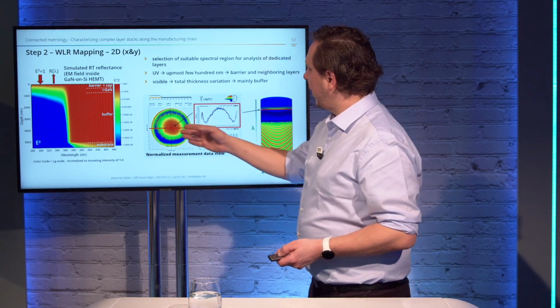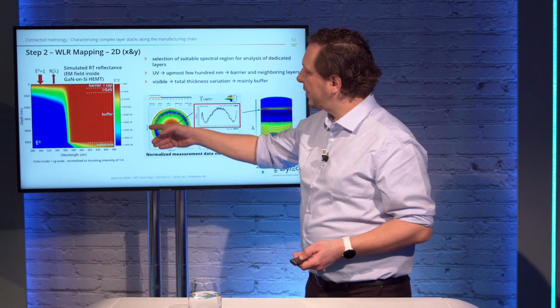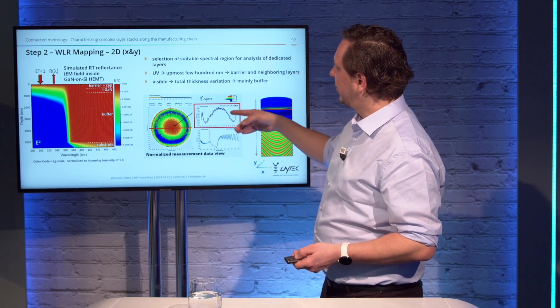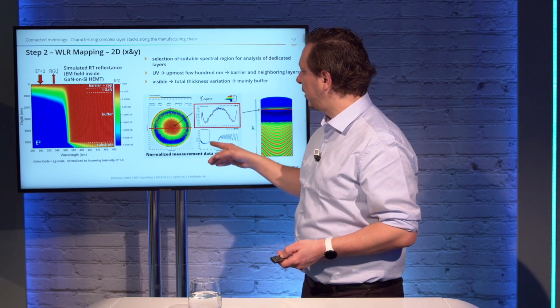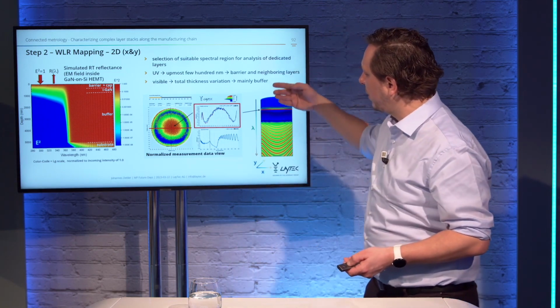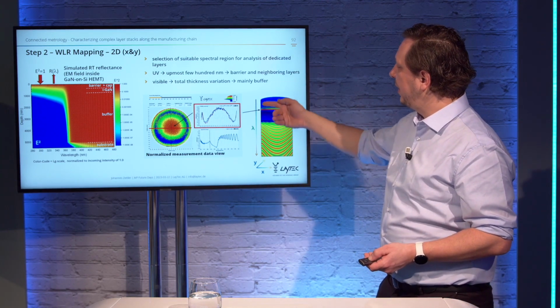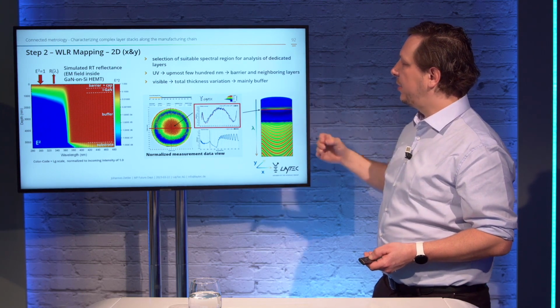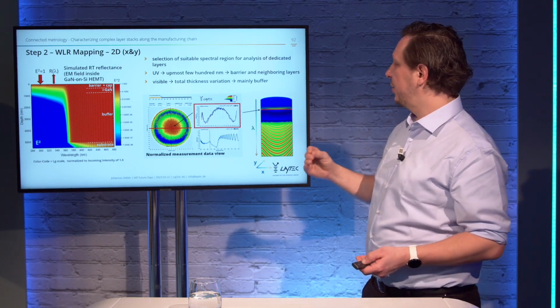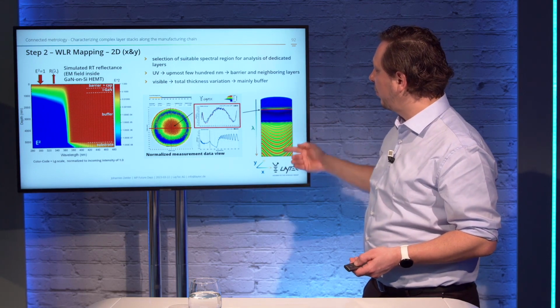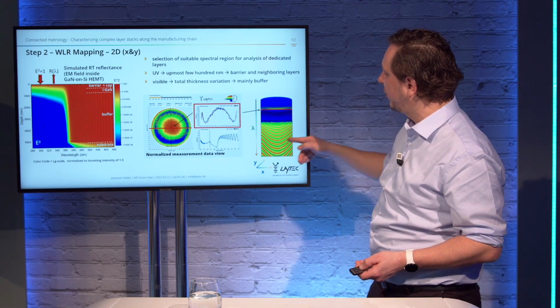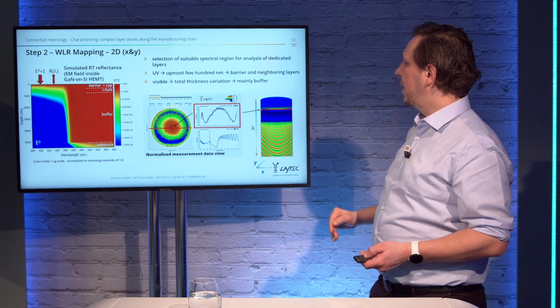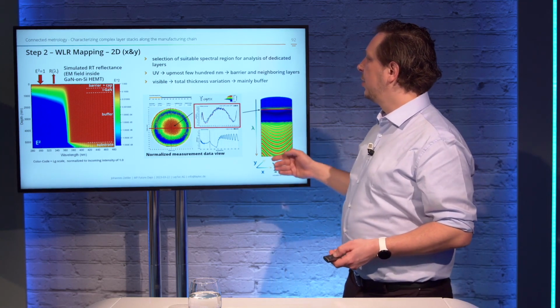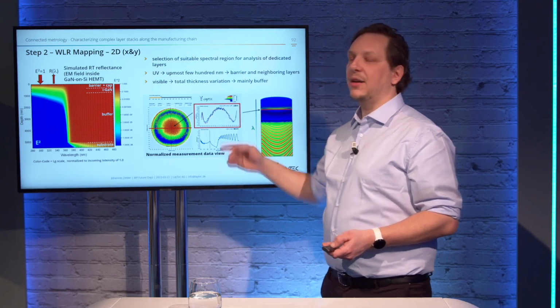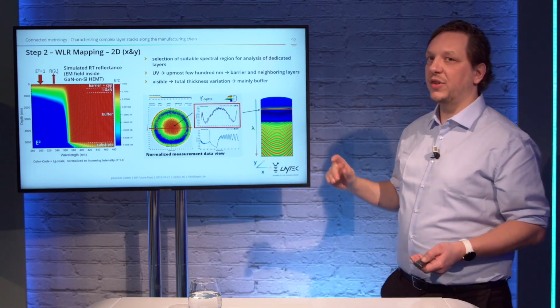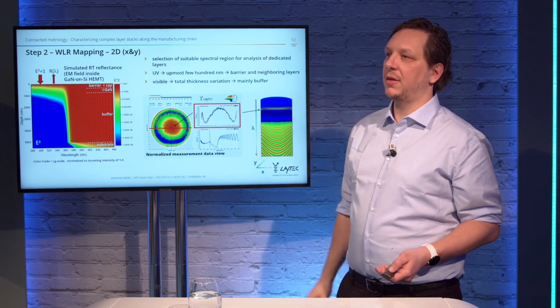And one other thing to illustrate it: if we cut through the wafer here, we get this profile for the wavelength that we have here, which is 320 nanometers. And if we look at it again for all wavelengths, for the short wavelengths we have a contribution dominated by the upmost layers, and for the longer wavelengths we have the Fabry-Perot oscillation. We see already here the inhomogeneity of the sample in X direction. And this we can use to have access to the total thickness variation of our stack, which is dominated by the buffer because that's the thickest layer.